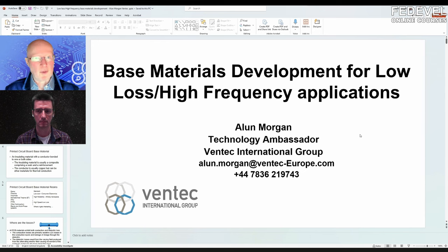We talked about the copper foil profile just a few minutes ago, the almost no profile, and how we're working very heavily to improve the profile of the copper foil as we bond to the material. Of course, the other side is also treated by the board shop. They roughen this material as well to bond it into their multi-layer stacks. So can you imagine? We produce a wonderful almost no profile film on the one side. They then make it like the surface of the moon because they want to bond it. And of course, they can take away all of the benefits that we've achieved because they don't understand it. Many board shops do understand it very, very well.